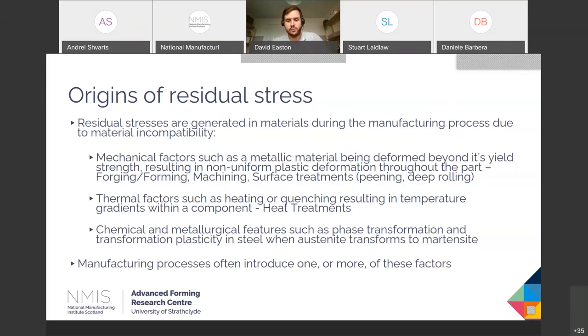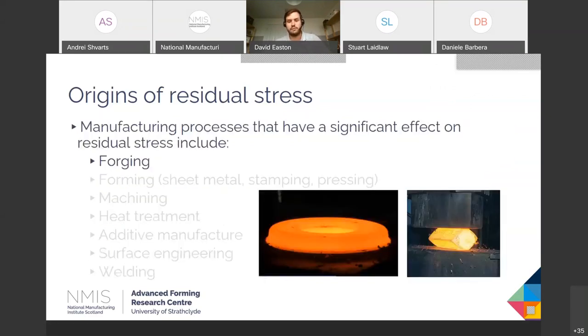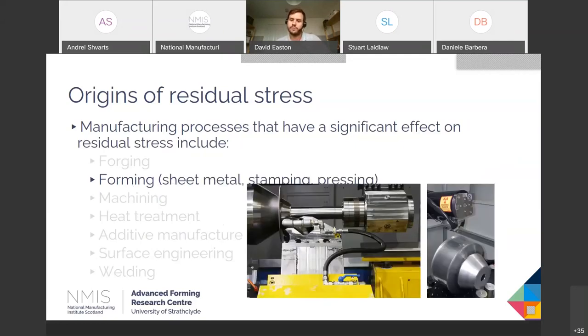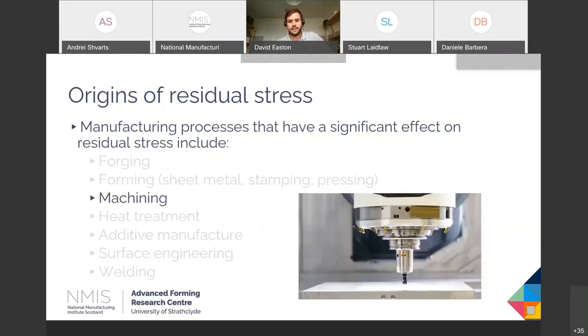Quite often manufacturing processes will introduce at least one and more likely two of these factors. Forging, for example, we have a mechanical influence here and we have a thermal influence on cooling. Forming, we've often got very high levels of deformation, severe plastic deformation, in order to shape the part as we want. And the result of that is residual stress. Machining. So machining and residual stress are very closely interlinked. Whilst machining itself can cause residual stress, the process itself can impart stress in the part. What we see quite often is that when we machine a part, we are releasing residual stresses that already exist and cause distortion. So we'll talk about this in more detail later, but anyone with a machining background is going to be familiar with the distortion problem, and that's thanks to residual stress.